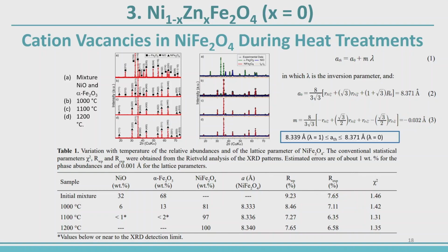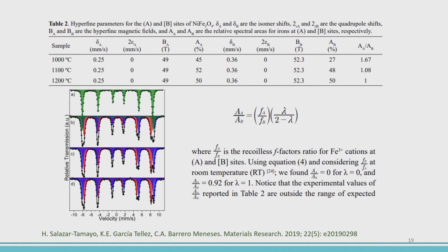We start with this idea, and then we check Mossbauer spectroscopy again. This is for the starting reactive. This is at different temperatures, and then we determine the area. Look at the area. I just want to point out the area ratio of the A to B sites. Look how it changes. It is high, and then as temperature increases, it goes to 1. How to explain this variation of the relative areas?